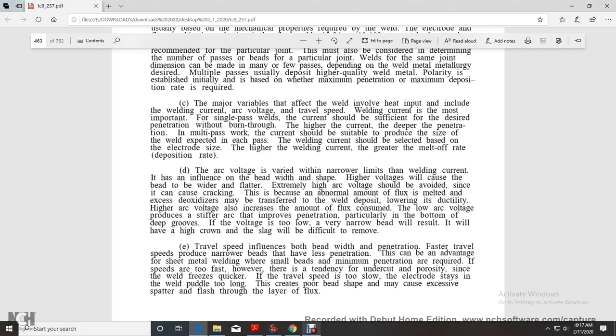Low arc voltage produces a stiffer bead but improves penetration, particularly at the bottom of deep grooves. If the voltage is too low, a very narrow bead will result, with a high crown and slag that will be difficult to remove.